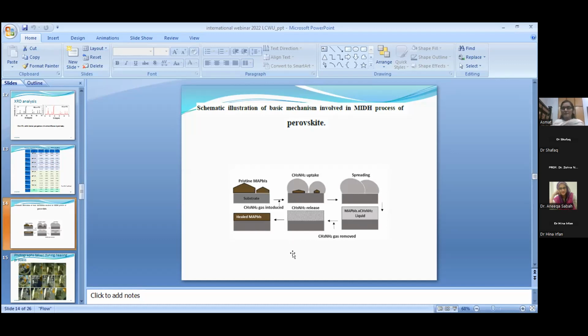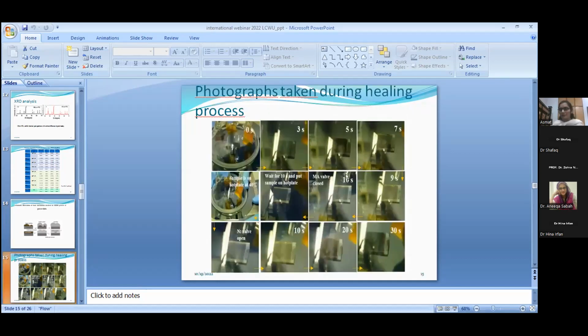So you can see the photographs which were taken during the healing process in my experiment. Now the valve is open, and you can see that after 10 seconds, the brown layer of the perovskite is dissolved into a transparent layer. And when we remove the methylamine gas, it takes about 30 seconds to crystallize the perovskite in the same dark brown color, with much improved infiltration of the perovskite in the pores of the nanostructures.